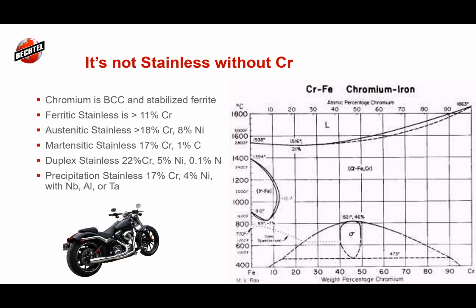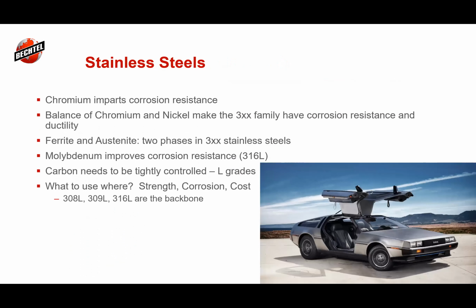But they all have some of the similar basic needs in the sense that they have the chromium that imparts the corrosion resistance, the chromium nickel balance sort of for the 300 series or the austenitic. And then someone will add molybdenum. But carbon is where I really want to talk. And what's really important with most of these alloys is controlling carbon. And we have the L grades and the H grades. It's trying to make sure that the carbon is not moving around and tying up the chromium and then losing its corrosion resistance. So we'll get into a little bit of the intergranular growth and the corrosion, the sigma phases and so on.